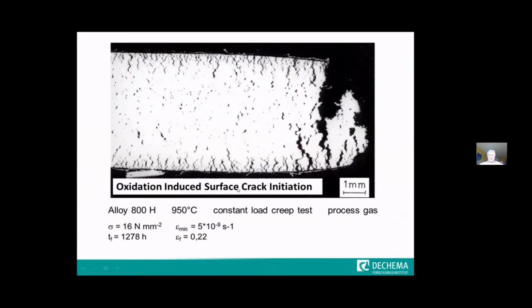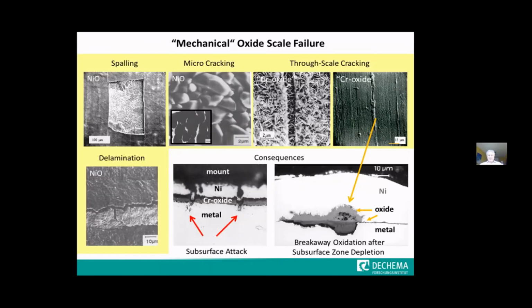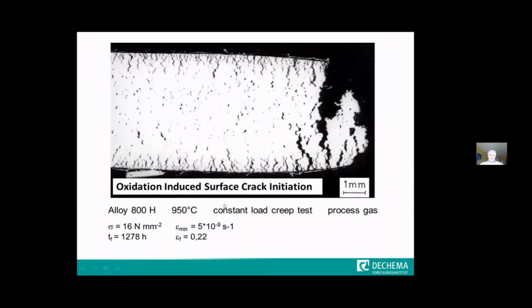So when we look at the next step after the crack formation in the oxide scale, it can happen that oxidation or corrosion leads to crack initiation from the surface. This is an example. We have hundreds of such cracks starting at grain boundaries, and these cracks have been formed due to oxidation along the grain boundaries and tensile stresses or tensile strains in a creep test here.